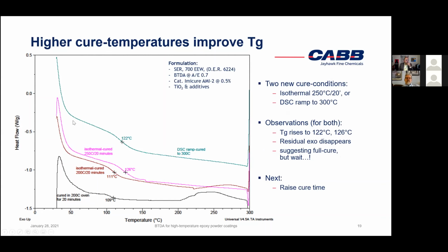And then when we took the uncured powder and just ramp cured it, not really isothermally, but a relatively fast ramp all the way to 300 and cooled down and tested the Tg, we got 122 Celsius. I would say more or less the same, but what it told us was that the 20 minutes was probably more important than the 5 minutes it got over 250. Then we wanted to do one more crazy experiment. We said, okay, we're going to go back to 200 Celsius for cure. We're not going to go over 200 C, just stay at 200, but leave it at 200 for a long period of time. And with long, we said, all right, 24 hours, that way we don't have any question.